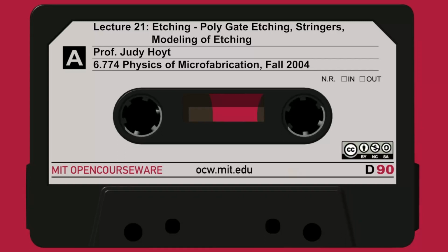This is just an example where you have etched a trench that looks like this, lined it with oxide, and then filled it up with polysilicon to make one of the plates of the electrode. The other plate of the electrode could be the surrounding silicon material. I took this out of an IBM Journal of Research and Development just off the web if you want to look at that in more detail. But so we need to make very high aspect ratio etches for these trenches. And we also need to care about the damage that we do to the silicon, because it's going to be part of a capacitor. So we want it to have smooth surfaces and things so that we don't break down the oxide, and we get a good electrical performance of the capacitor.